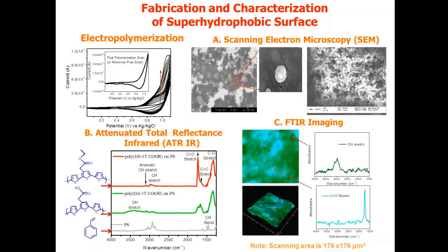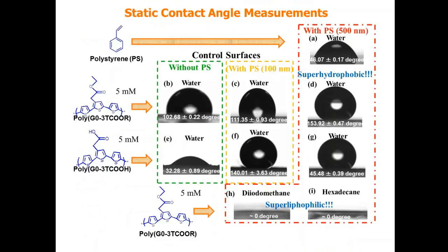Now, it's interesting in that with this, actually, we discovered that this type of coatings have very good properties of what we call a super hydrophobic effect. The super hydrophobic effect means it hates water or is self-cleaning. And we achieved this on this polymer material, polythiophene, that was polymerized on top of those colloidal particles. On the other hand, we found that these coatings actually are super oleophilic, meaning they love oil.